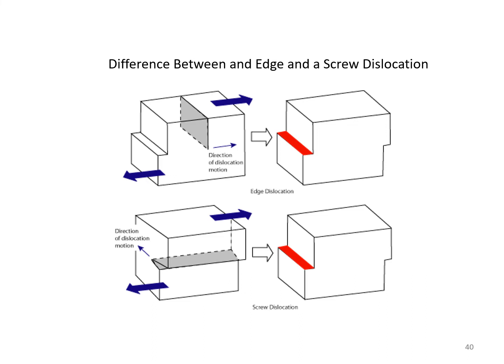But there are two modes in which dislocations can be introduced. One is edge mode. Basically, if we pushed half of this crystal in this direction, you could shear it just by breaking a line of bonds here and pushing the extra half plane across the crystal. The other mode is the same shear, but you start at one edge here and you break a line of bonds along this line, and then you tear the material in a line going across that direction.